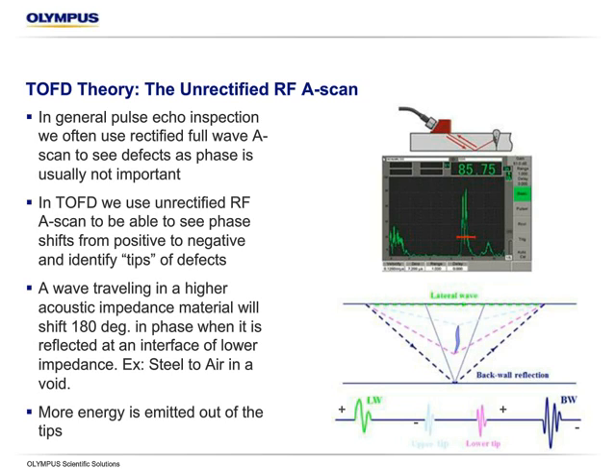So we can see on the display here, if we normally set up a time of flight diffraction setup and we're just looking at the lateral wave and the back wall, we're going to go from the baseline, and the peak of the lateral wave is either going to be positive or negative depending on whose instrument you're using and how it's wired. But the back wall is always going to be 180 degrees or the exact opposite, in this case negative from that positive peak.